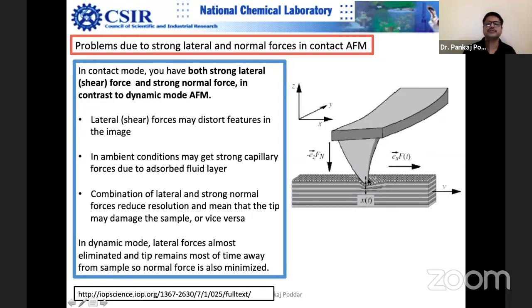So this mode is known for giving you high resolution images, and it is considered fast. If the set point is not set properly, this can damage the sample as well as the tip. And if the tip gets blunt, you may end up getting worse resolution images rather than high resolution images. So high resolution depends upon the quality of the tip.